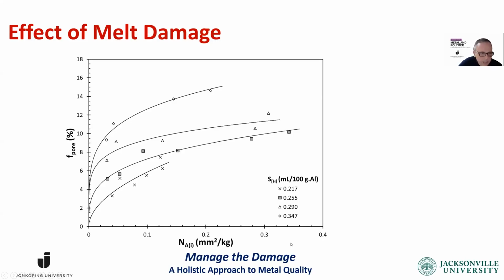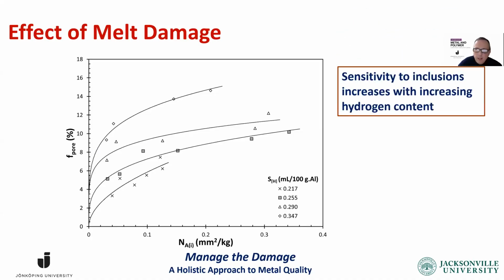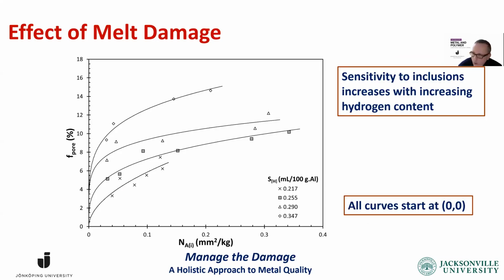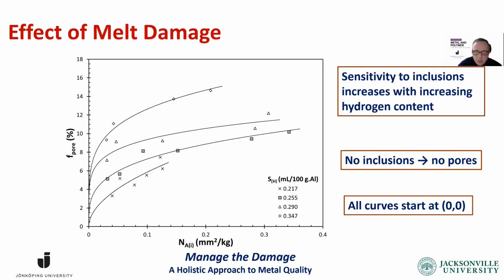basically, okay, the higher the hydrogen, the higher the pore volume. Okay, that makes sense. But the sensitivity to inclusions increases with increased hydrogen content. Okay, makes sense as well. All curves start at 0, 0. So if there's no damage, that means the hydrogen content would not matter. So that's basically what I could learn from this.